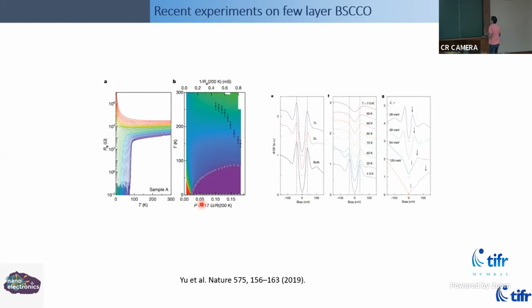Not just that, they demonstrated that by peeling it down to a single unit cell, its properties in terms of TC and its spectral behavior are identical to bulk. People before these experiments surmised that the superconductivity lives in 2 dimensions in this copper oxide plane, but this is the first direct evidence down to the unit cell, or some people have also done half a unit cell, which is essentially just one copper oxygen plane in the crystal. The superconductivity is as you expect in bulk.